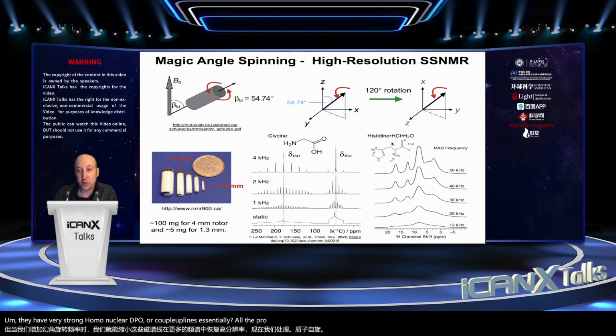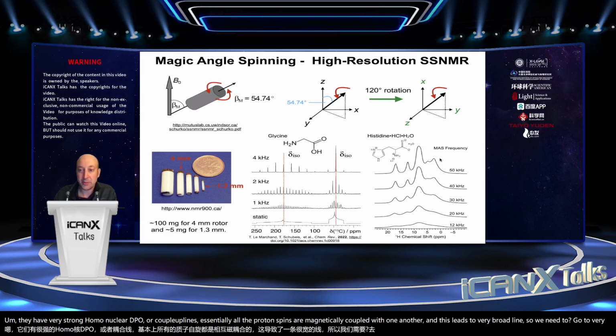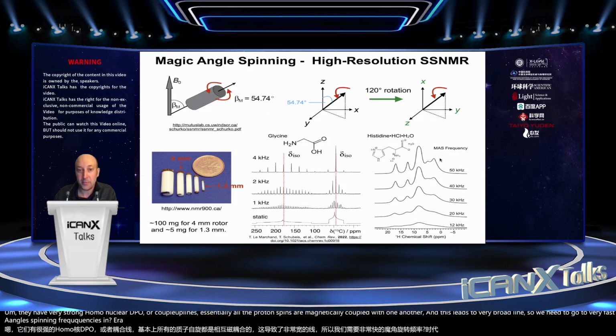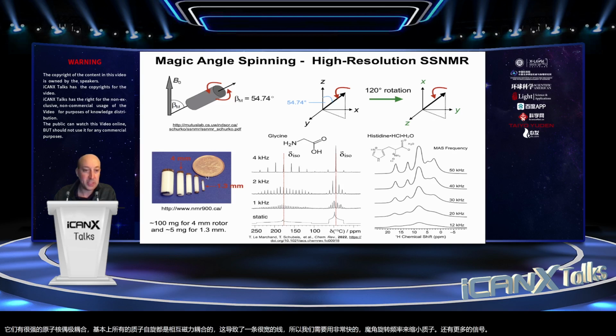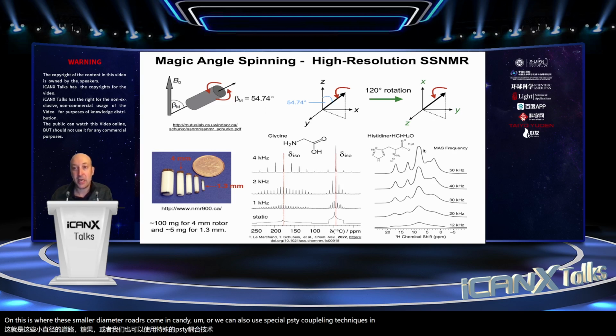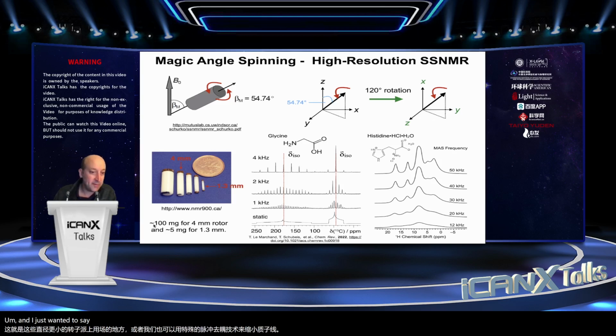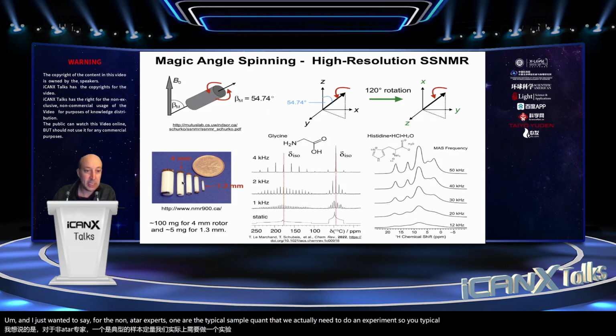Essentially, all the proton spins are magnetically coupled with one another, and this leads to very broad lines. So we need to go to very fast magic angle spinning frequencies to narrow up the proton NMR signals. This is where these smaller diameter rotors come in handy. Or we can also use special pulse decoupling techniques to narrow up the proton lines. And I just wanted to say for the non-NMR experts, what are the typical sample quantities that we actually need to do an experiment? So you typically need around 100 milligrams of material to pack this 4mm rotor.